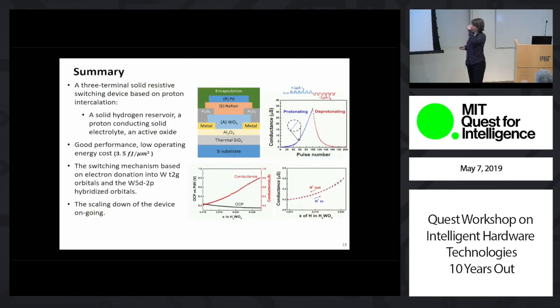Okay? So in summary, which is what I have just said, we could demonstrate an all-solid-state proton intercalation device, which can give us multiple conductance states by extracting hydrogen from a solid reservoir and inserting it into an active channel oxide, tungsten oxide in this case. And based on the conductance ranges that we could obtain, number of states, the energy consumption, reversibility, and stability, it looks quite promising.